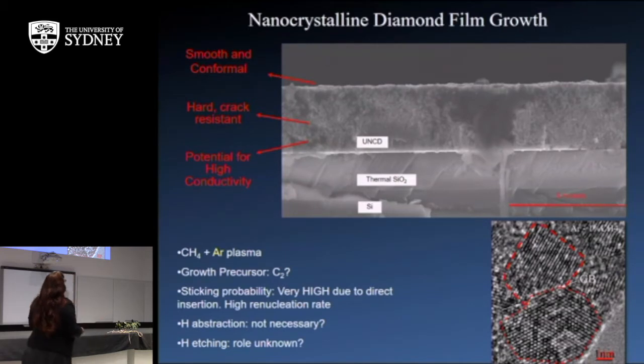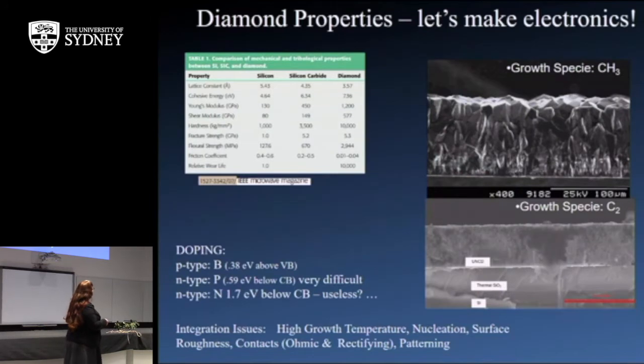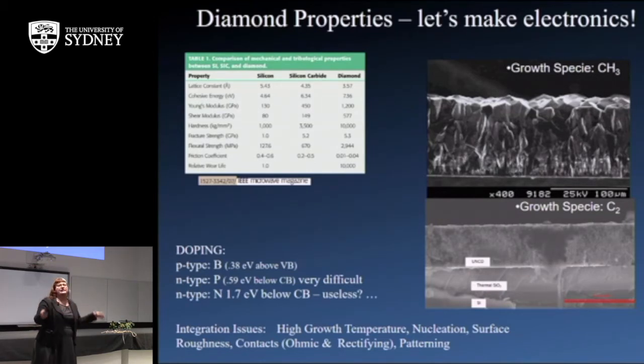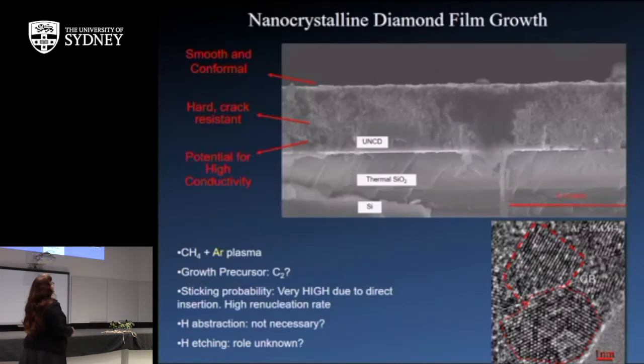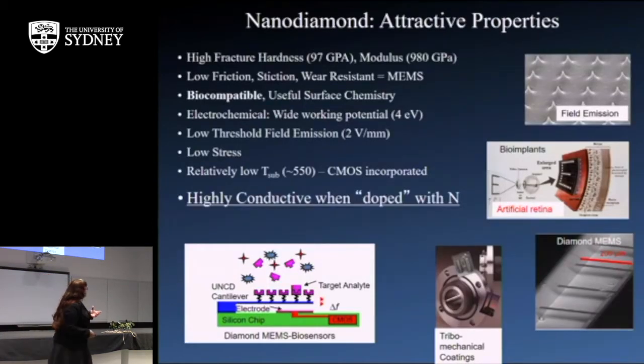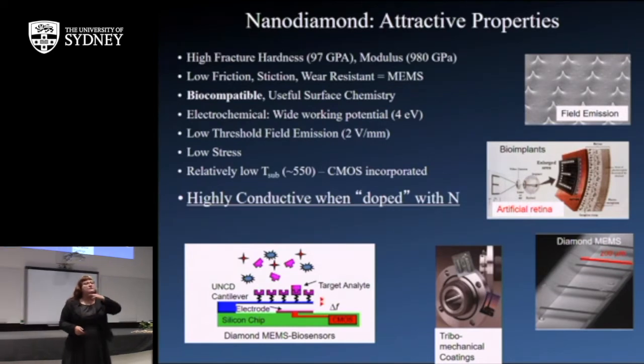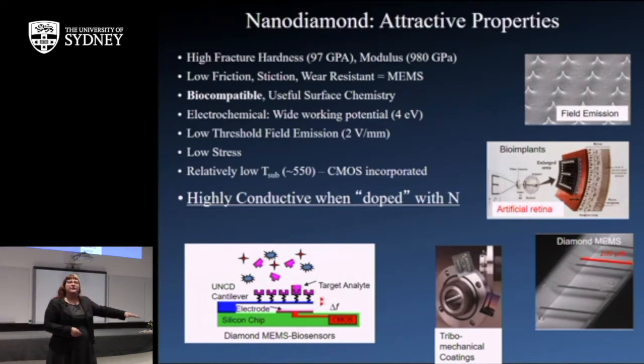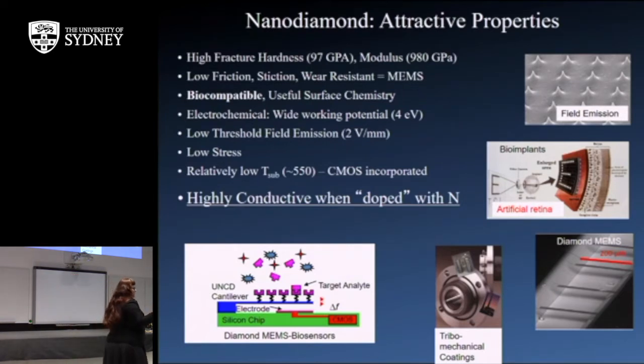But anyway, this is a very interesting material because you can actually dope it N-type with nitrogen, and you don't get these super deep states. It means that you can actually get it to work reasonably well, which diamond isn't supposed to do. And it has some really interesting properties. It has very interesting field emission properties, and it has very, very low friction. And very low, something we call stiction, which is when you first move something on a surface. And you don't get that unless you have a very smooth film.